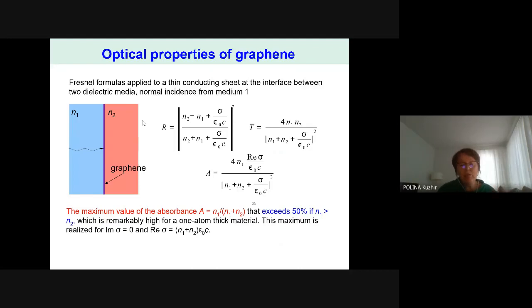But for many device applications, you will need more—you will want to have perfect absorption. There is a very simple way of achieving this perfect absorption with a thin layer of graphene: just put this graphene in between 2 dielectric media. When radiation comes from the side with a higher refractive index, you could achieve very high, almost perfect absorption with just this one graphene layer.